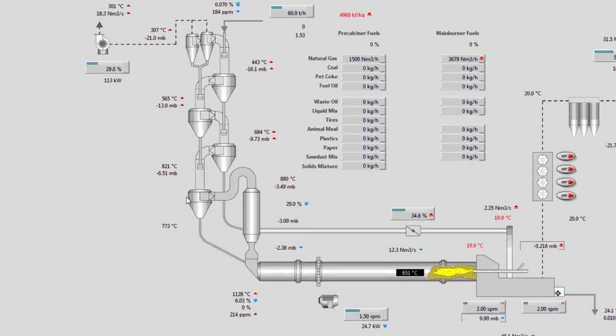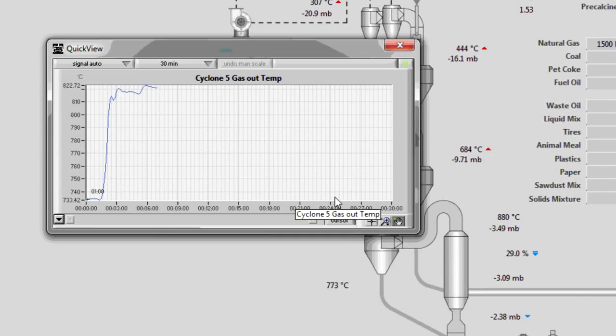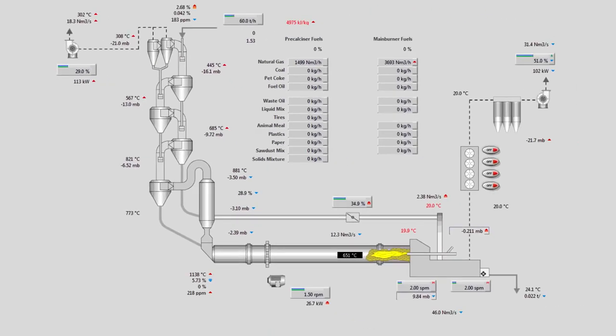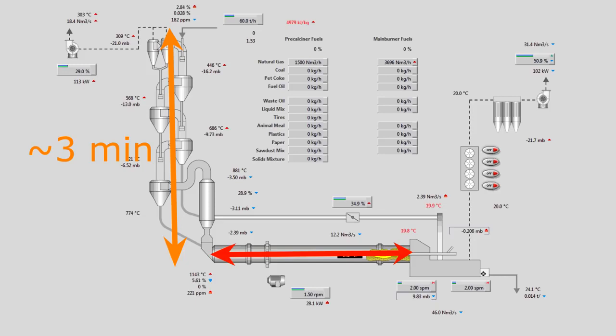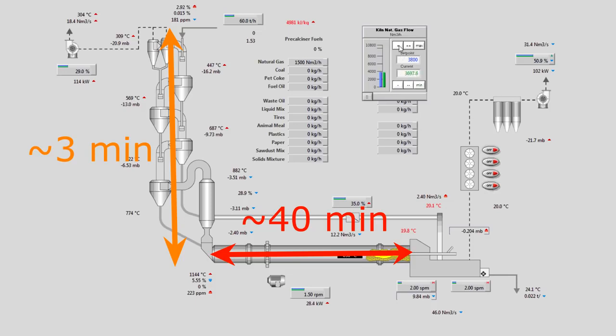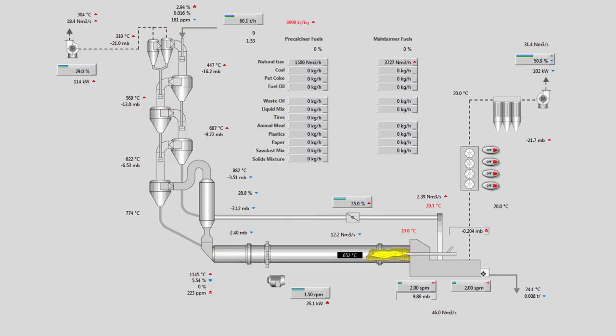Nice gas temperature at stage 5. You can see the effect of firing the precalciner. It is important to start the precalciner rapidly after feeding. Remember, it will take only about 3 minutes for the material to reach the bottom of the preheater and get well precalcined, while it will take around 40 minutes for the material to reach the burning zone. This is why we have some additional time to heat up the BZ before the material gets there.